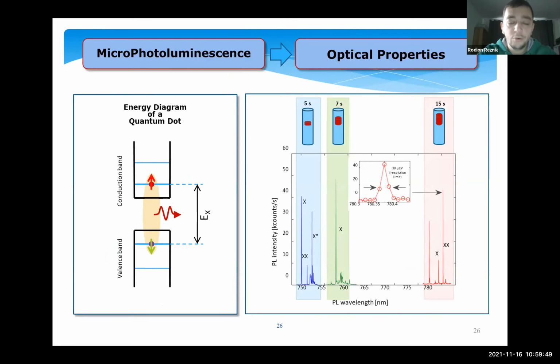After this, in DTU, we started to study single nanowires with these quantum dots. Here we have a small principal scheme again of these nanowires with different quantum dots. We have 5 seconds of formation, 7 seconds of formation, and 15 seconds. And again, even from single nanowires, we have different emission energies from the quantum dots, from 750 to 790 to 800.